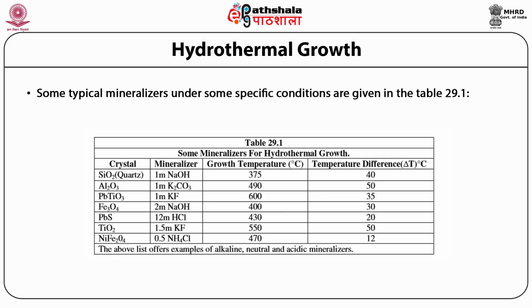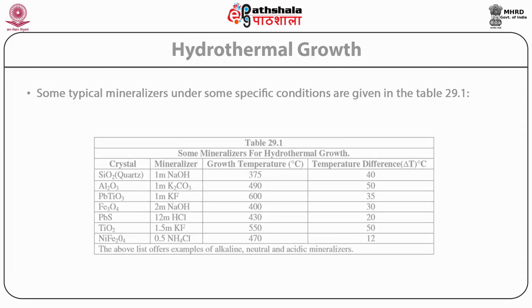For the growth of TiO2, the mineralizer used is 1.5m KF. The growth temperature is maintained at 550 degrees centigrade. The temperature difference is maintained at 50 degrees centigrade. For the growth of NiFe2O4, the mineralizer used is 0.5m NH4Cl. The growth temperature is maintained at 470 degrees centigrade, whereas the temperature difference delta T is maintained at 12 degrees centigrade. The above lists that I referred to offer examples of alkaline, neutral, and acidic mineralizers. Now we shall talk about advantages of hydrothermal crystallization.